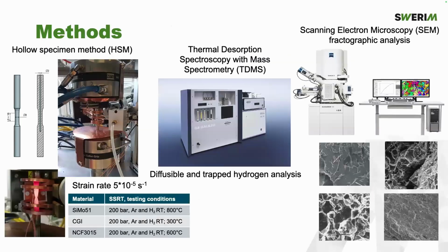Let's move further. Classically, the same way as presented so far from Sefer's side, the hollow specimen methodology, coupled with post-mortem measurement of hydrogen to see whether we have some uptake and how this hydrogen is affecting the possible trapping sites, as well as fractographic observation. Conditions: SSRT tests running at 3 different temperatures, which you can see in the table, at 200 bar, with argon as the inert environment and a hydrogen environment as well.